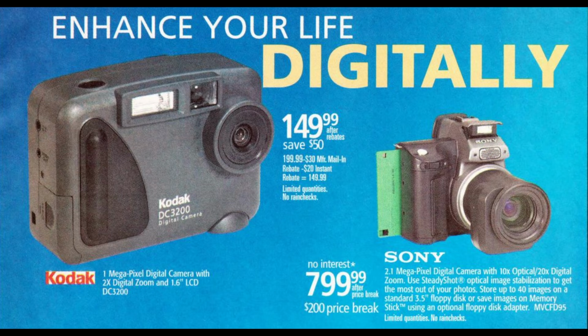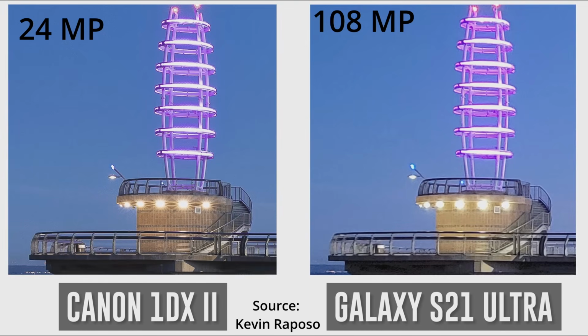For some buyers, perhaps they are focusing too much on hardness. It can be a bit like the megapixel wars of digital cameras back in the early to mid-2000s. The number of megapixels is one measure of quality, but it can be misleading because the quality of the optics is much more important than the number of megapixels. A low-end steel or a poor heat treatment can be used to give a high Rockwell hardness number, which looks impressive on the spec sheet, but ultimately the performance of the knife may be poor.